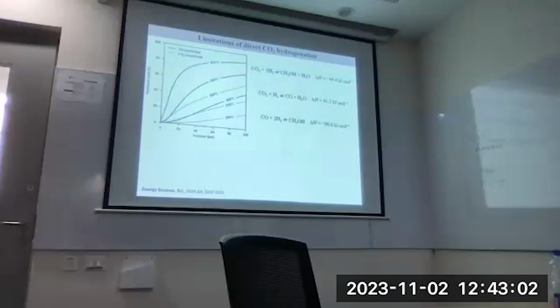If you look at this process, it's reasonably exothermic, but you're using 3 moles of hydrogen, and an equilibrium gets established after some time. So even with the best catalysts we use for this process, you don't convert more than 30 to 40% of the CO2. You're using 50 bar, high pressures, and around 250 degrees. If you see here, with the CO2 feed, you're not getting much methanol.